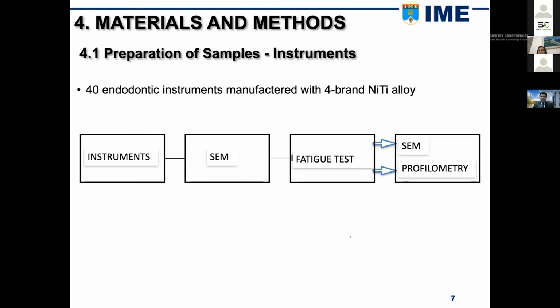The morphology of the samples of wires and instruments was observed under a scanning electron microscope before performing the rotation bending test. After the bending and rotation test, the samples of wires and instruments were again analyzed in the scanning electron microscope. The average roughness and the valley depth of the samples were quantified in the profilometer.